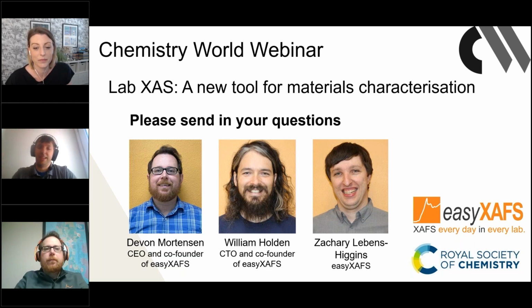Yes. So typically the simple solution for air-sensitive samples, particularly if they're not too air-sensitive, is Kapton sealing, where you use Kapton tape to seal the sample. That typically works for at least a few hours, depending on how sensitive the sample is. If you need even better sealing, you can use specialized sealed cells that you could seal in a glove box, for example. And that works for pellets or liquid samples. That's easily put into the instrument and works for a variety of elements.